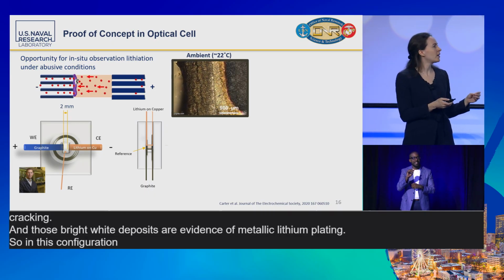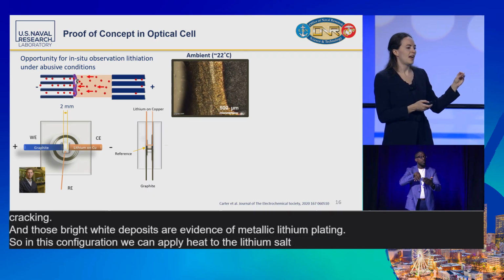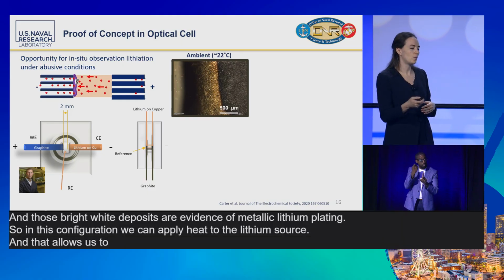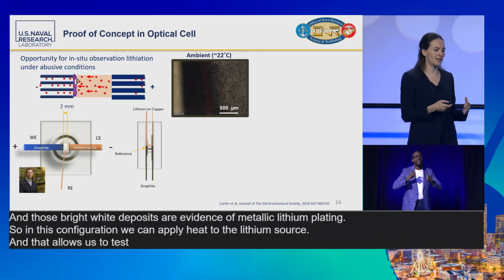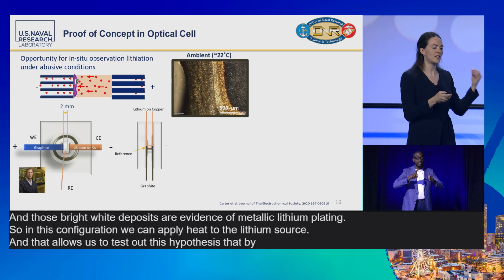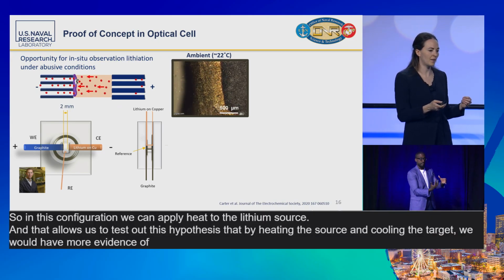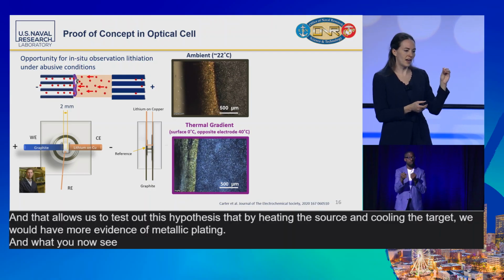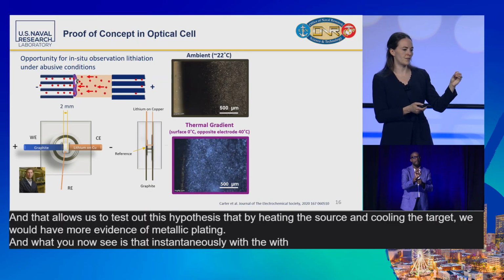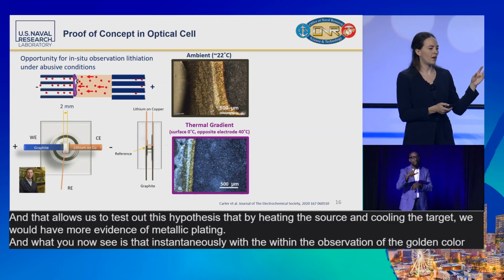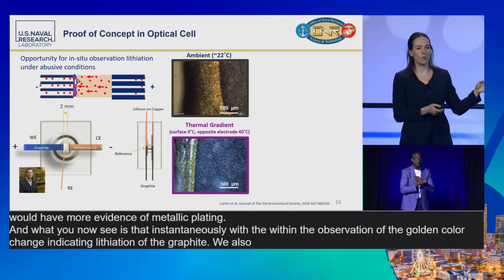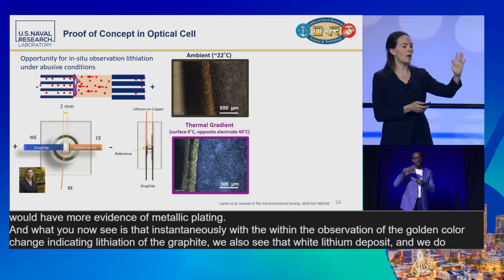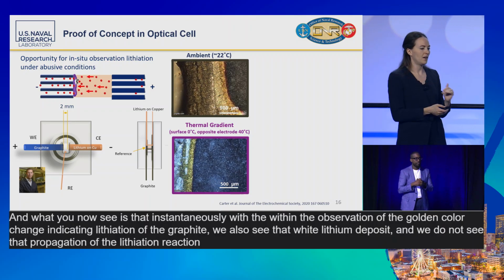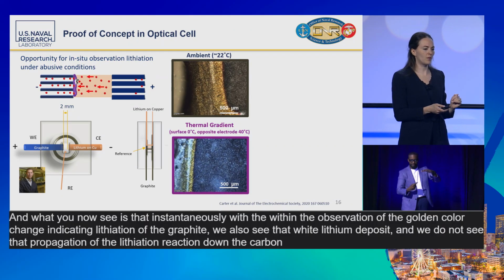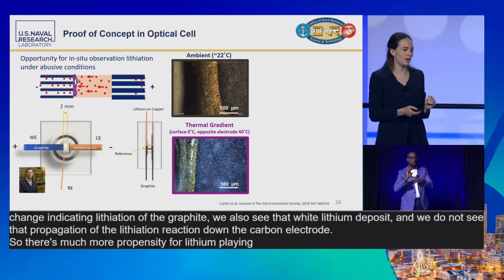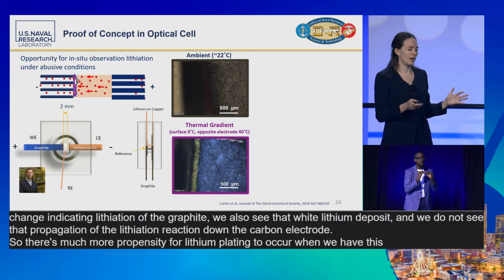So in this configuration, we can apply heat to the lithium source, and that allows us to test out this hypothesis that by heating the source and cooling the target, we would have more evidence of metallic plating. And what you now see is that instantaneously within the observation of the golden color change indicating lithiation of the graphite, we also see that white lithium deposit. And we do not see that propagation of the lithiation reaction down the carbon electrode. So there's much more propensity for lithium plating to occur when we have this thermal gradient.